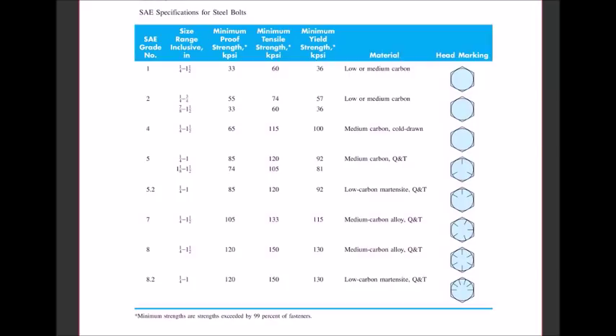So it makes as much sense from afar as any other Imperial system of units. But if you look at the markings on the head, you can figure out the grade number, and given the size range, you can find the minimum expected proof strength. Okay. So a proof strength of a grade 5.2 is 85,000 psi. So that means that 99% of fasteners will have at least 85 kpsi of proof strength or more.